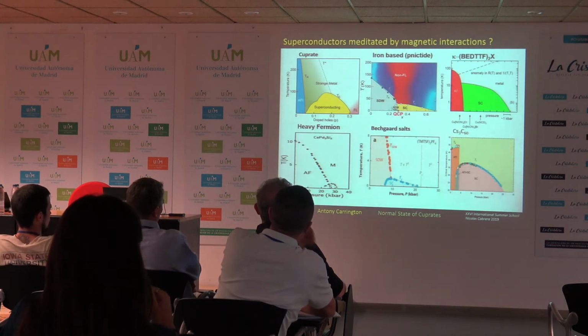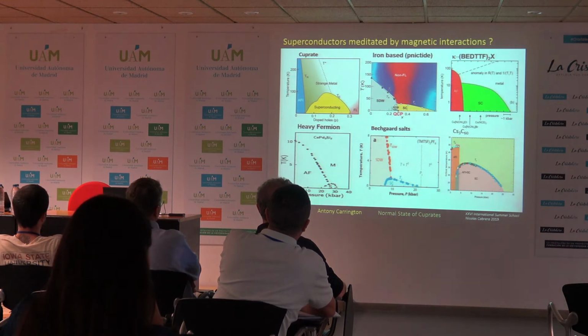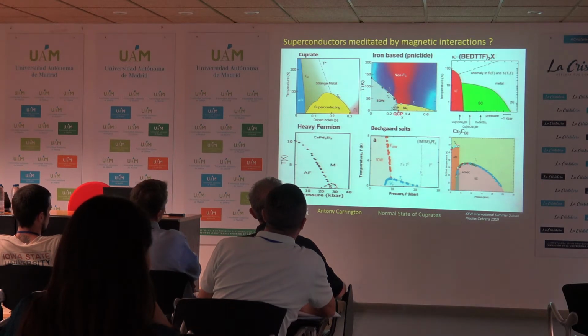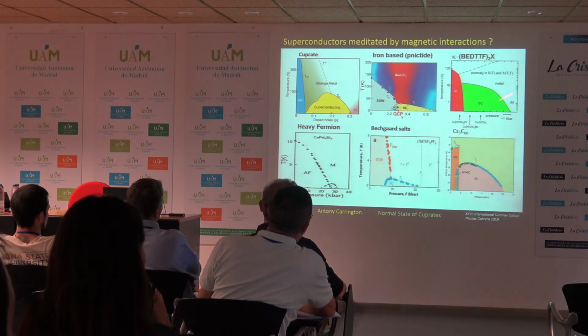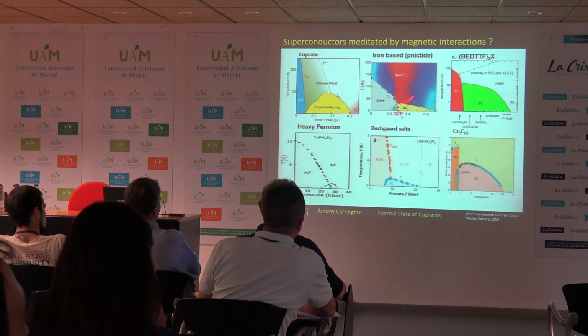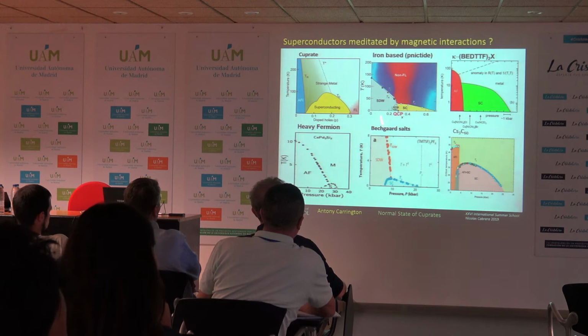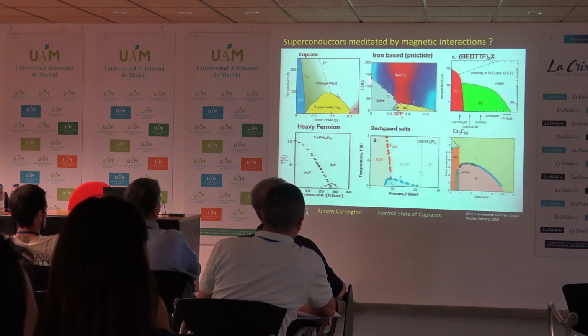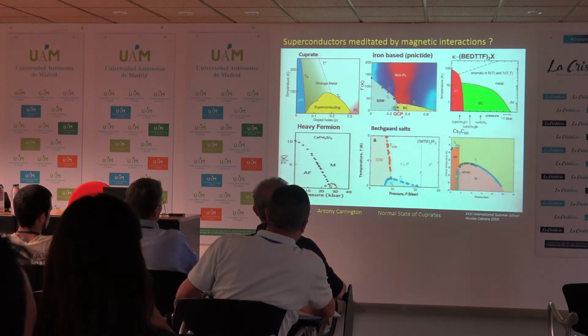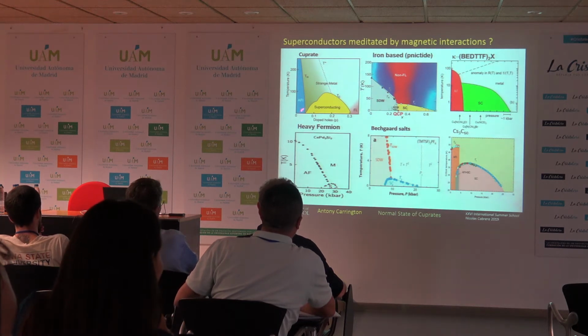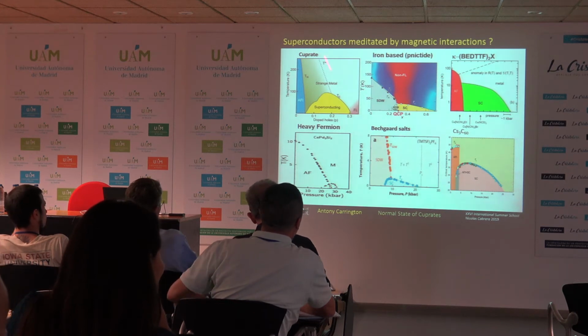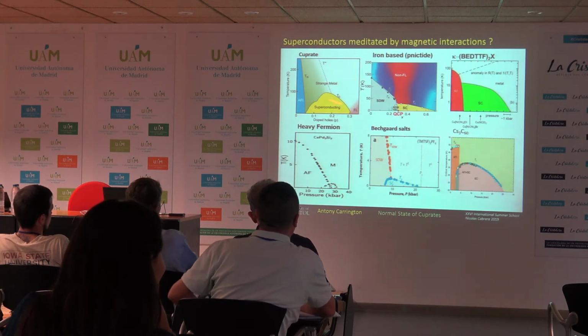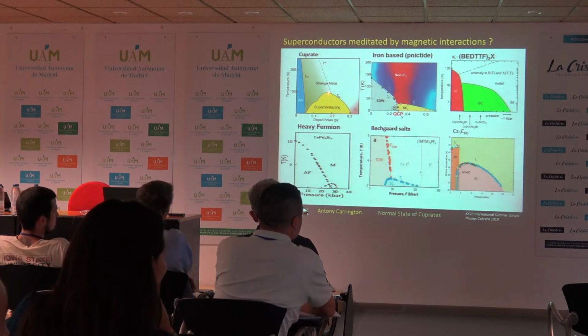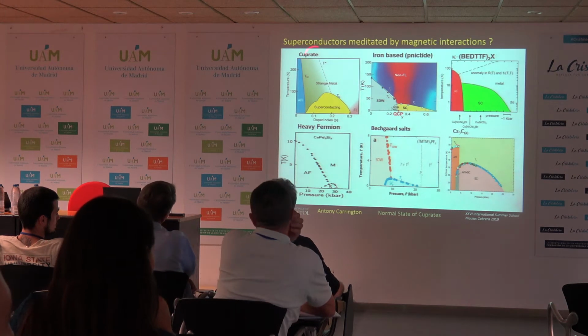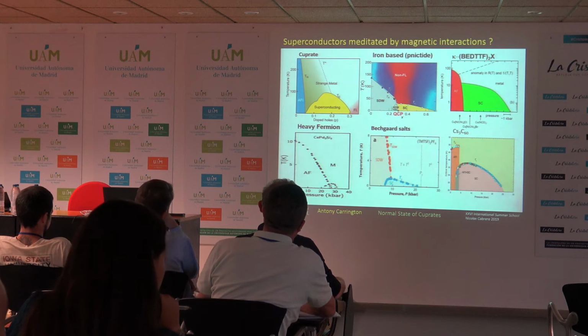Now, when we're looking at these materials, we're thinking about them nowadays in the context of a whole bunch of other materials that have been discovered to be superconducting on the edge of magnetic phases: heavy fermions, organic superconductors, and more recently these iron-based materials. What you notice for a lot of these is that superconductivity produces this little dome located at the end of the antiferromagnetic phase, in the iron-based and heavy fermion materials. In the cuprates, it's not so obvious what that competing phase is. At the end point of this antiferromagnetism, Tc is 0, and so people have been looking for other competing phases which have a quantum critical endpoint which approximately lines up with the maximum in Tc. The contenders for that are the pseudo-gap phase or the charge density wave.